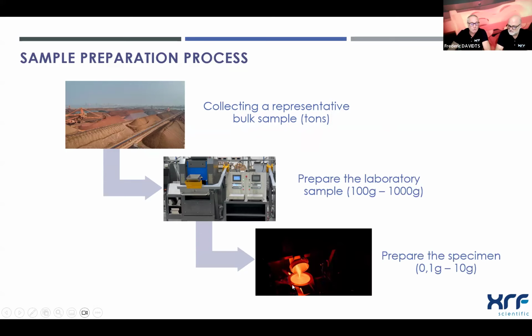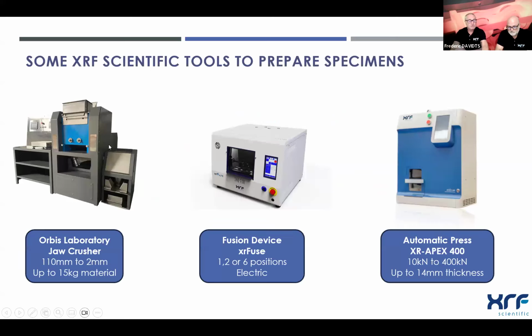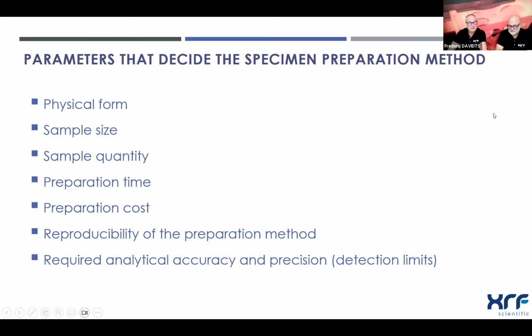So in our case now, we will talk about fused beads preparation. In general, we have a specimen of 0.1 to 10 grams, but for fused beads, in general, we have less than 1 gram of sample. So 1 gram representing the tons of material. Remember this. Tools are also being provided by XRF Scientific to make sure that you do have a decent laboratory sample available. I show just a couple of the tools here. We can see a jaw crusher, a fusion device, and an automatic press, all tools that can help you in the laboratory to provide your specimens that go into the spectrometer.